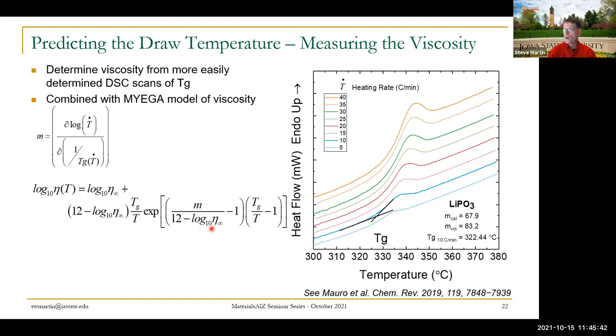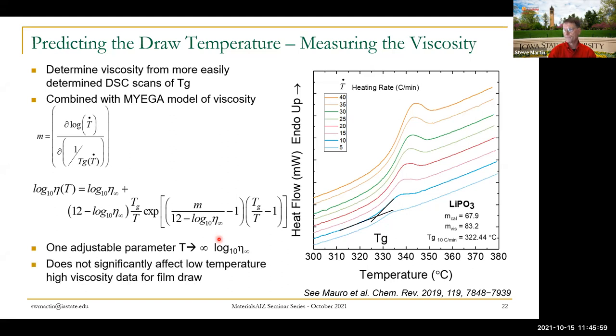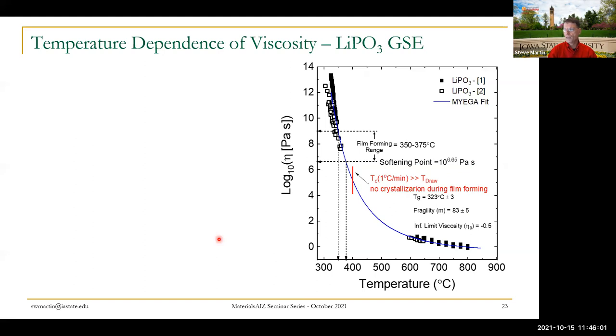We know from other measurements what the infinite temperature viscosity is, because they don't change that much. We can measure the Tg of the glass, and so we can model the viscosity and then predict the temperature that we want to draw these films at. And then that's the plot here.